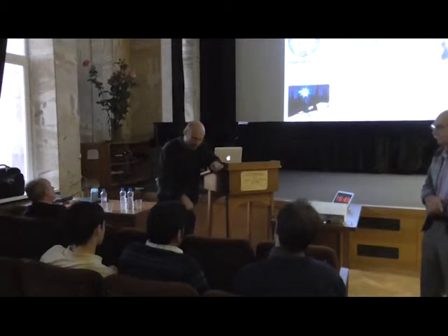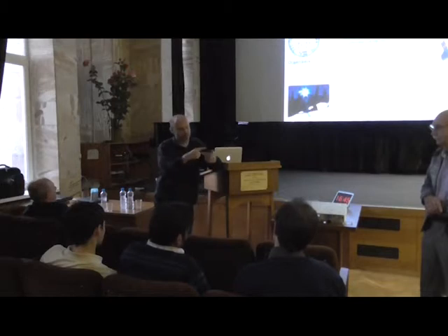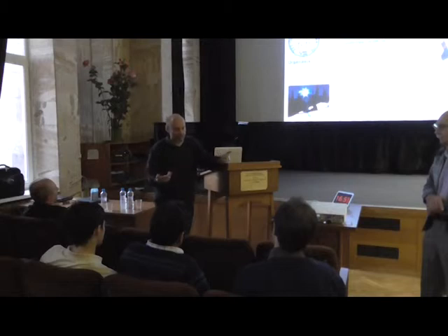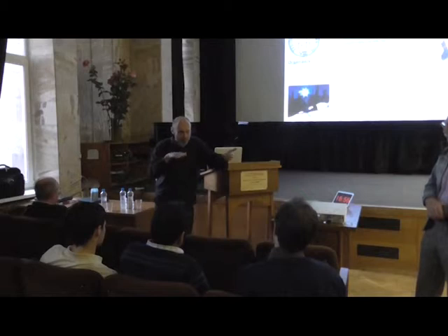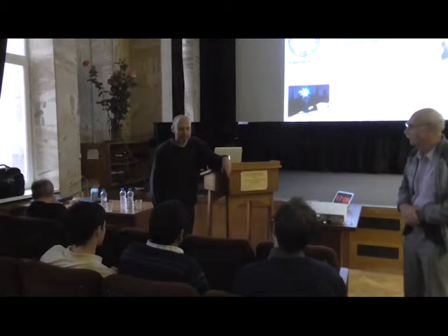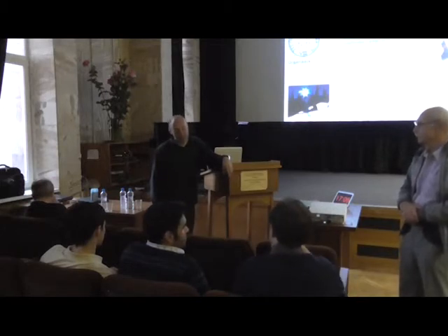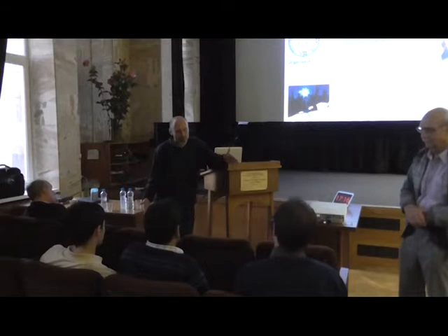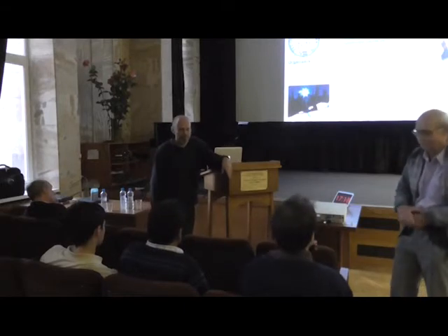It won't just go back. Basically, to transfer momentum, it should go like this. It was negative, but it cannot be absorbed by the system because the change in the electron energy is very, very small. So essentially, you don't have to take into account the electron; it's gone long, long ago before the atom starts moving. So what you actually do is give kinetic energy to one atom, right? Yes, I assign initial kinetic energy to one of the atoms in my system and then do molecular dynamics with density functional theory forces. Okay, thank you.